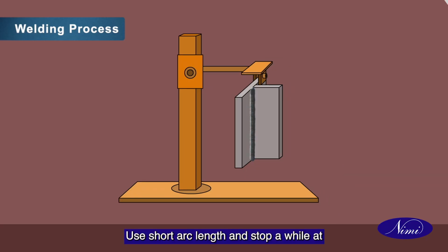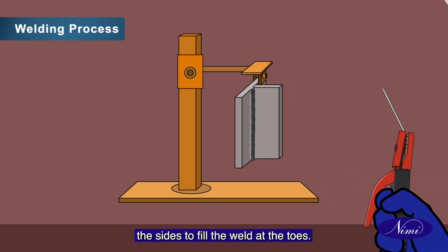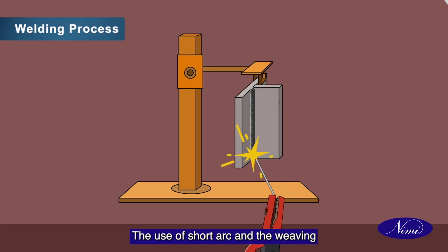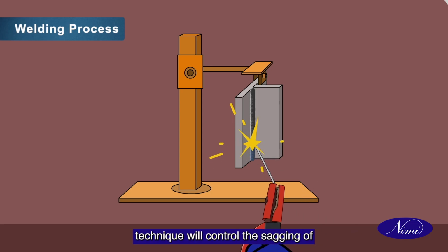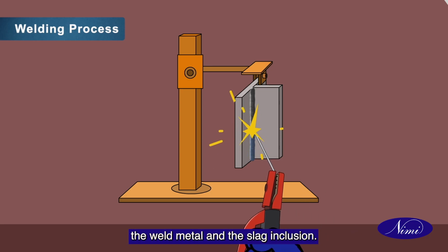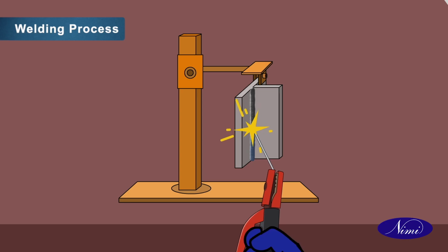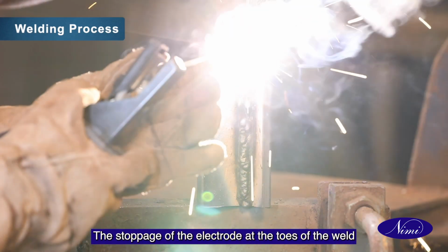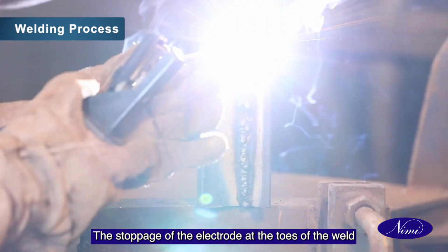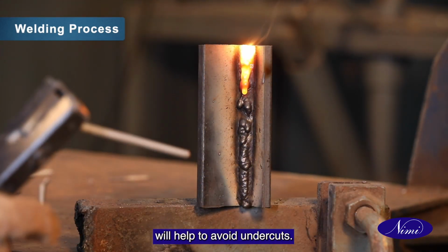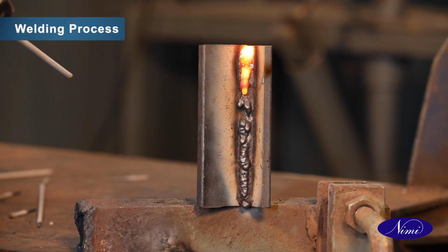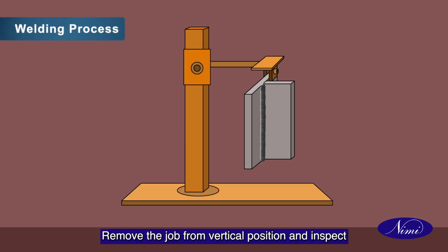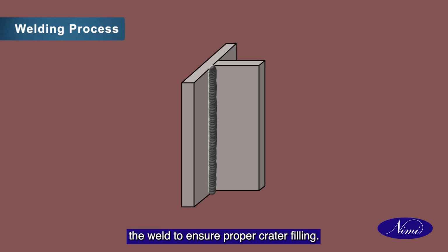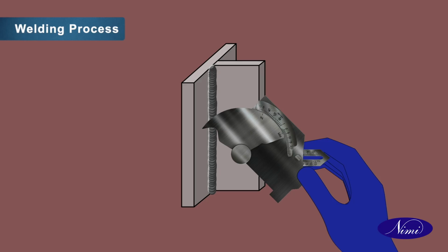Use short arc length and stop a while at the sides to fill the weld at the toes. The electrode tip points upwards due to the electrode angle. The use of short arc and the weaving technique will control the sagging of the weld metal and the slag inclusion. The stoppage of the electrode at the toes of the weld for a moment in the weaving motion will help to avoid undercuts. Remove the job from vertical position and inspect the weld to ensure proper crater filling.